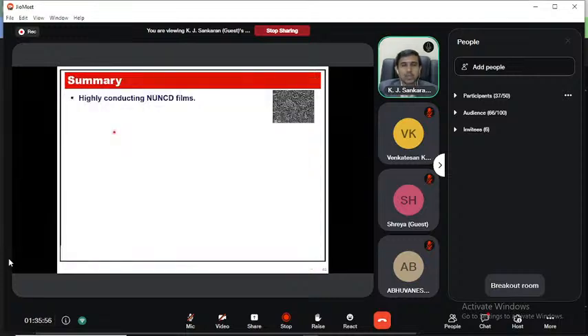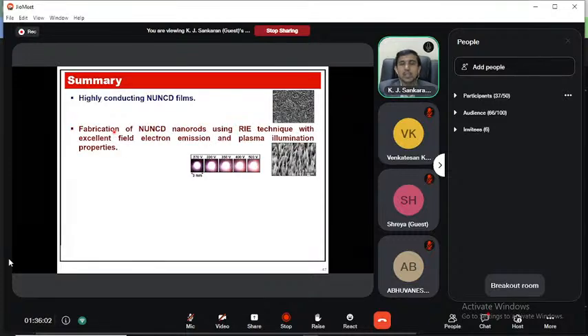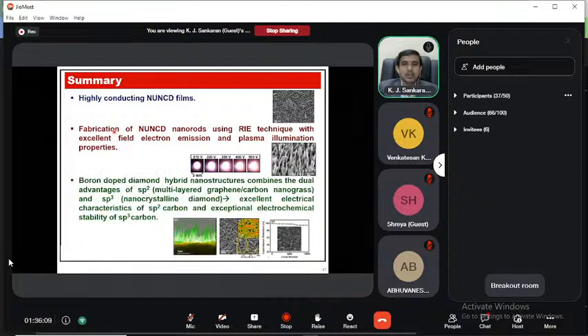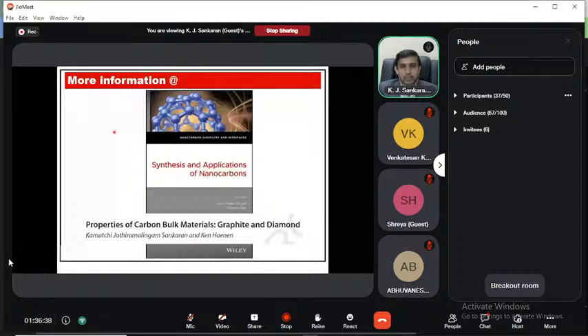So as a summary of my work, we have fabricated the nitrogen incorporated UNCD films, particularly for electronic applications like plasma illumination devices. Then we have fabricated boron doped hybrid diamond with the diamond as the core and the graphene as well as the carbon nanograss as the shell, which gives the diamond exceptional electrochemical stability. This shows that these diamond electrodes and diamond cathodes have very good advantages in applications like electronics as well as electrochemical supercapacitors. More information you can find in this book chapter that we have written about the comparison of the graphite and the diamond.